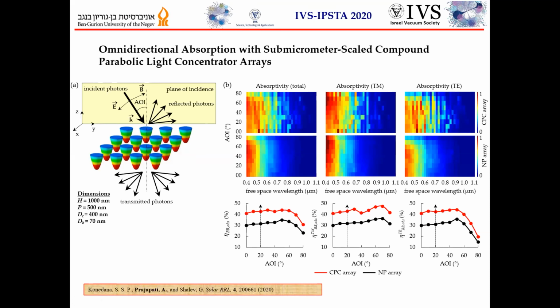Evidently, the CPC array exhibits enhanced omnidirectional broadband absorptivity with peaks reaching wavelengths greater than 800 nanometer. The peaks and spots are present here, but in the nanopillar, they are absent. It seems that it is limited to wavelengths below 600 nanometer. Also note that while the angle of incidence dependency of nanopillar absorptivity is homogeneous, the angle of incidence dependency for the CPC array is more complex and exhibits hot spots like here, here, here, here. Also, as expected, the absorptivity under TM illumination is higher and more omnidirectional than the absorptivity under TE illumination for both CPC array and nanopillar arrays.